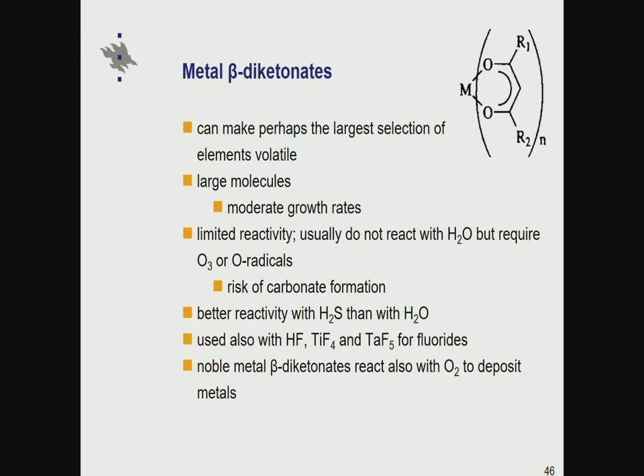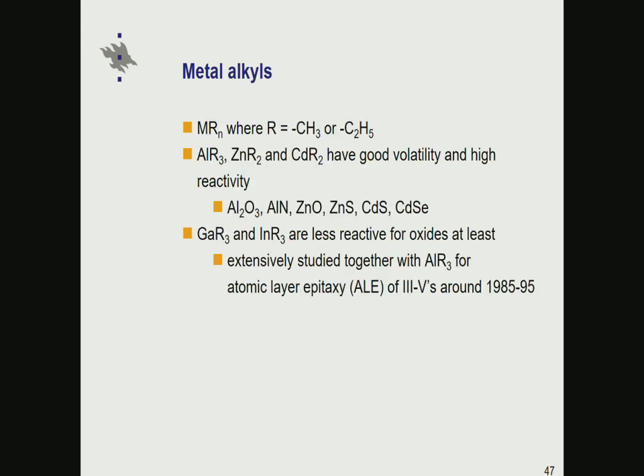The main problem here is that these are quite large molecules, which means moderate growth rates. Also, in case of oxide deposition, they don't react with water, but require something more aggressive, especially ozone or oxygen radicals from plasma. And at that time, they also lead to a risk of carbonate formation. They show, in many cases, better reactivity towards hydrogen sulfide than towards water. And they can also be used for depositing fluorides and metals, as I will show you a little bit later.